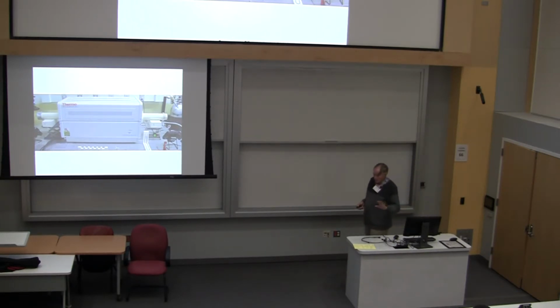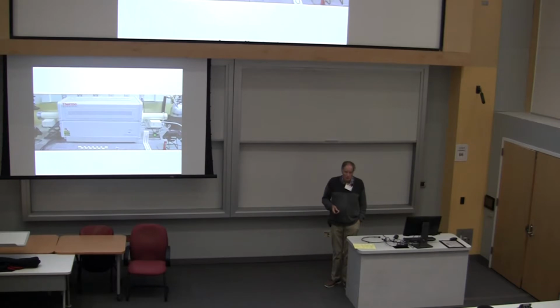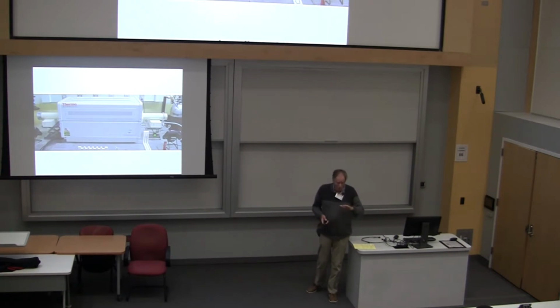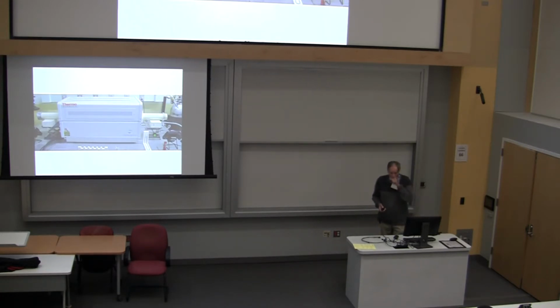There's another problem that happens at those temperatures with aluminum. There's some point at which aluminum oxide starts to dissolve in aluminum, and there's a couple of things that happen with that. One is that when you melt aluminum it always has a small cover of Al2O3 on it, no matter what you do, right? When you get rid of that, the vapor pressure of aluminum starts to cause you problems. I mean, if you're growing in quartz, you're already at 1200 degrees or close to 1200.